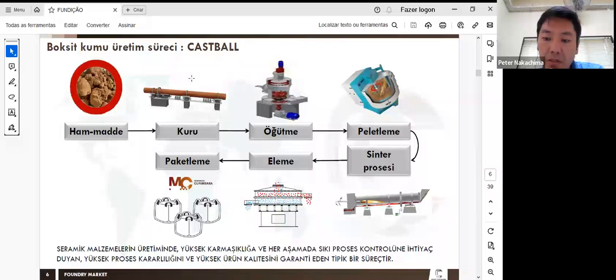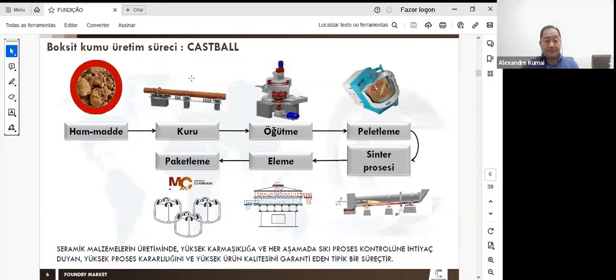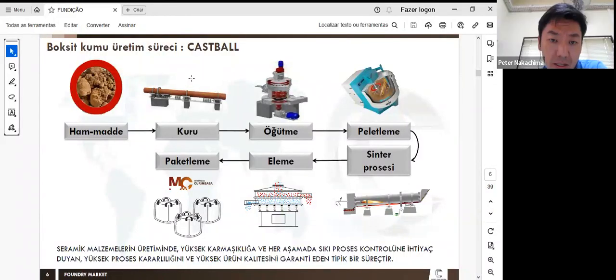And it's important to mention that during all the steps of the process, we collect samples to monitor the process. For instance, we monitor the moisture during drying, the size of the powder, the particle distribution of the powder during milling, the size of the spheres during pelletizing, the density during sintering, and so on. And additionally, all these steps are fully automated to guarantee the stability of the process and the quality of the product.